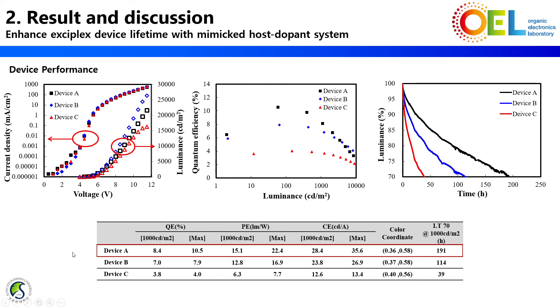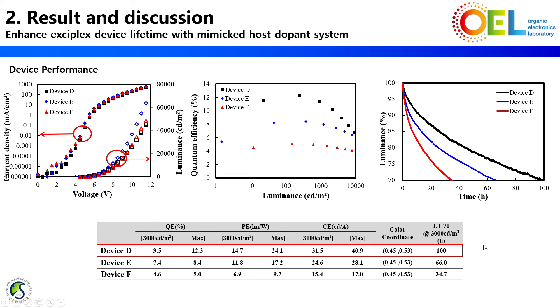Not only this efficiency enhancement — the device lifetime was also largely extended from 39 hours to 191 hours at 1000 cd/m². Then, this performance improvement was also shown in X-Plex host yellow fluorescent OLED devices. Not only device efficiency improvement, but the device lifetime was extended from 34.7 hours to 100 hours at 3000 cd/m².